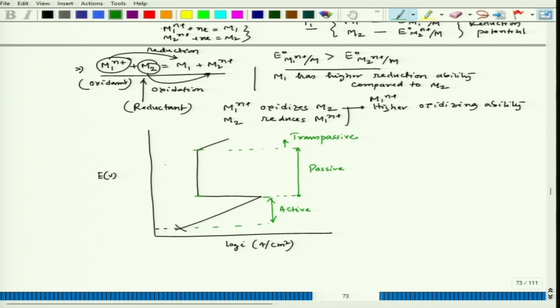Now, in this case, initially the material is in the passive zone. So, it maintains passivity. Now, interesting is this is the cathodic part, corresponding to IC, or the cathodic current density. Now, the corrosion rate would be here, which is I corr equal to IP, as per mixed potential theory. This particular point lies very close to this transpassive zone.